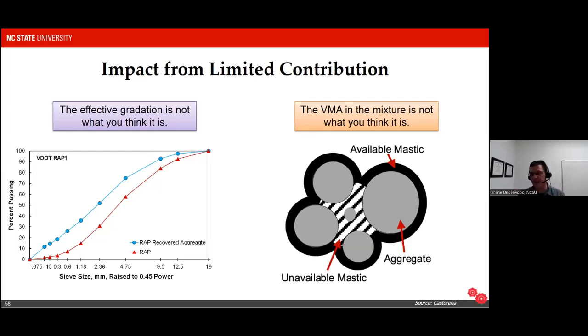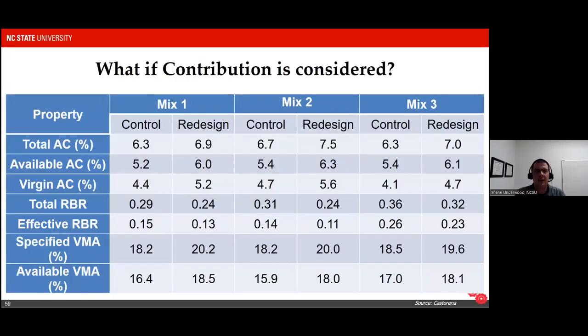Again, the basis of this is, we need to think very, very carefully when we deal with these recycled materials about how they interact with our virgin materials and yield good or, in a negative case, bad performance. So what she's done is taken a couple of three mixes. Each of those mixes, she's created two different variants, a so-called control mix, which is basically standard practice on mix design. What you'll notice is because not all of the binder is active, we actually have a fairly low recycled binder content. She redesigned that mixture by taking into account how much binder was actually contributing.